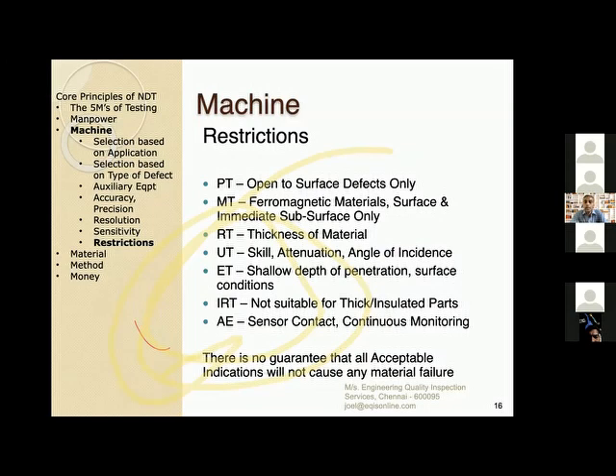And for UT, the operator dependence is a very important aspect. The equipment as such holds only 25% of detectability and the remaining 75% goes with the skill set of the person. And we have electromagnetic testing, which again requires a conductive surface and the depth of detection is very, very low. And if I'm talking about infrared thermography, again, if it's insulated, I will not be able to use that technique.